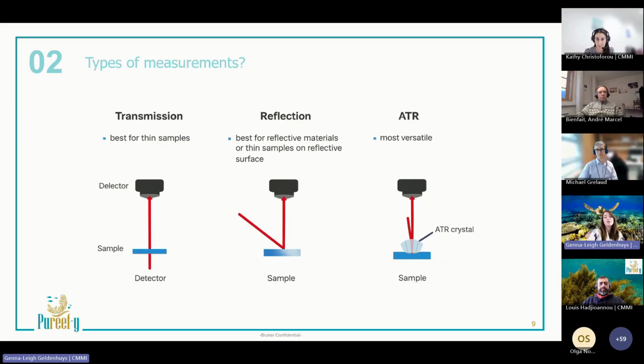For transmission, the infrared light shines straight through the sample before being detected. This technique is useful for thin samples like tissues or films. With reflection, the infrared light bounces off the surface of the sample prior to detection, making it the go-to technique for analyzing reflective bulk samples or samples with reflective films. The ATR uses a crystal, which is usually made of germanium. The crystal touches the sample, and the IR light passes through the crystal and enters the first couple of micrometers of the sample. Now, this technique is the most versatile of the three and can be used to analyze a wide range of samples from electronics to cloth, all without sample preparation, but it does also have its limitations.